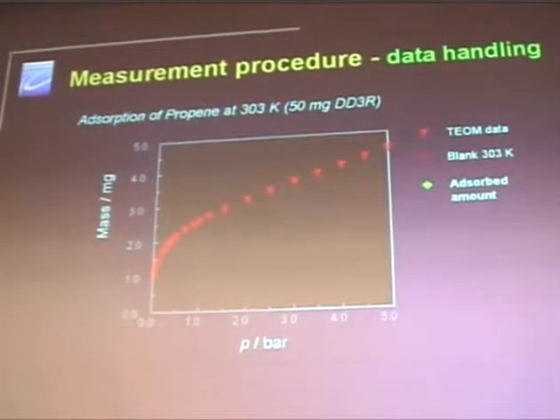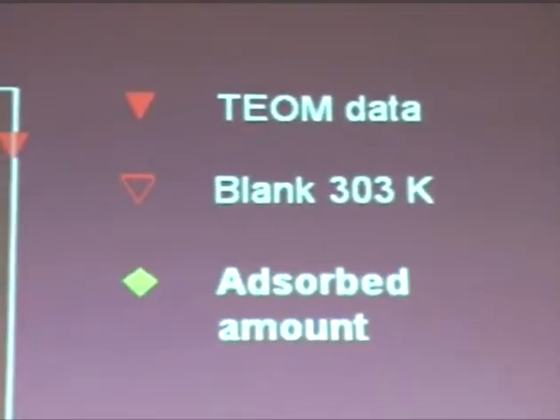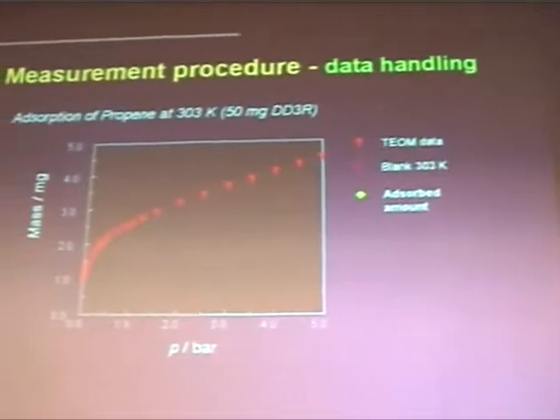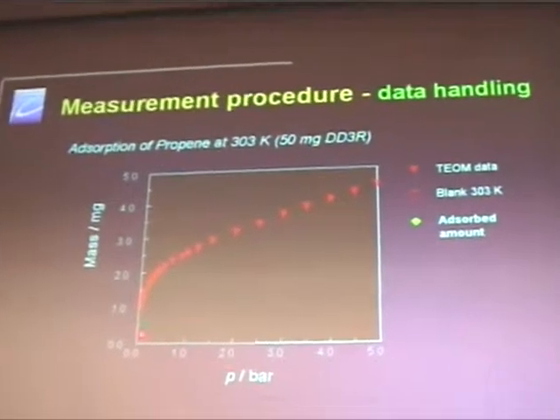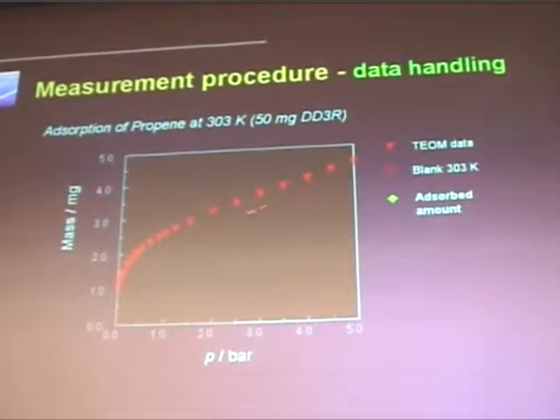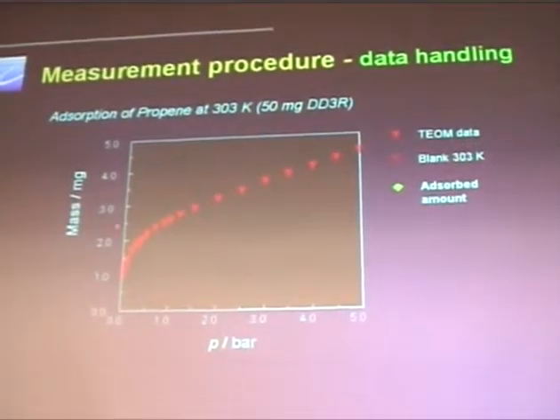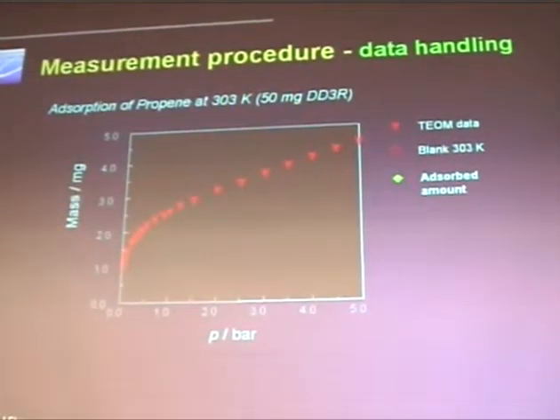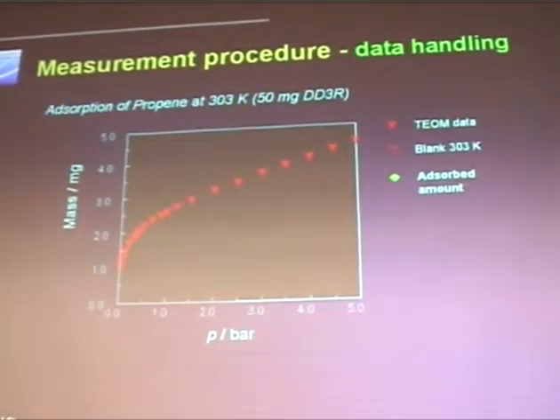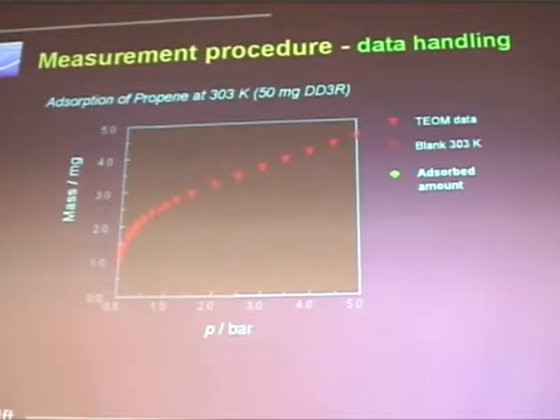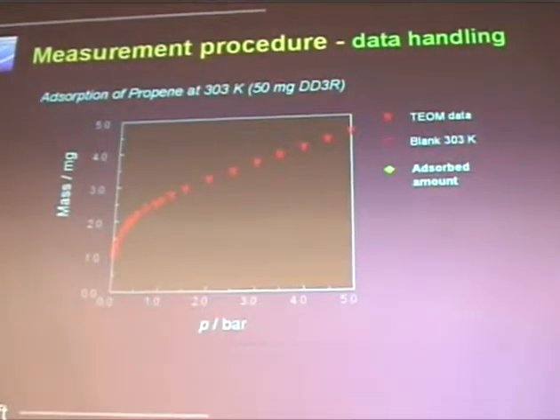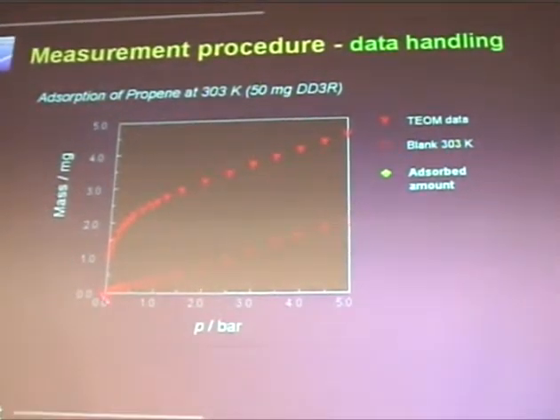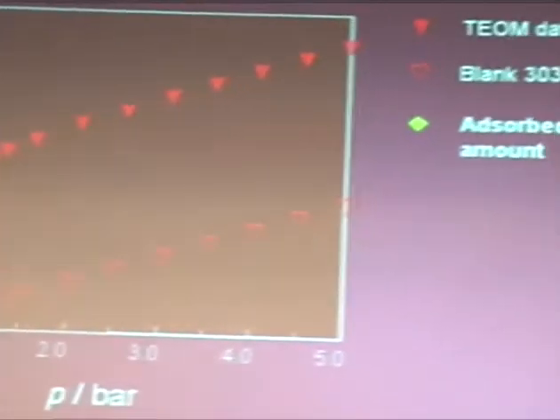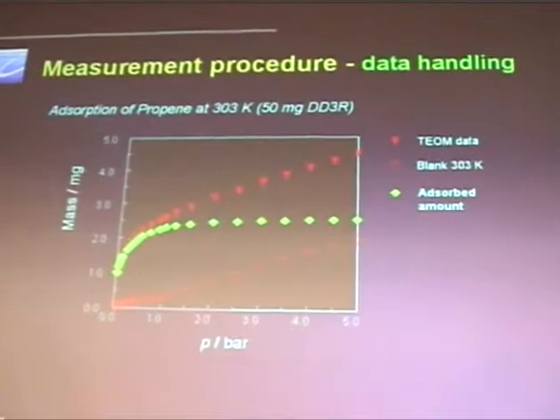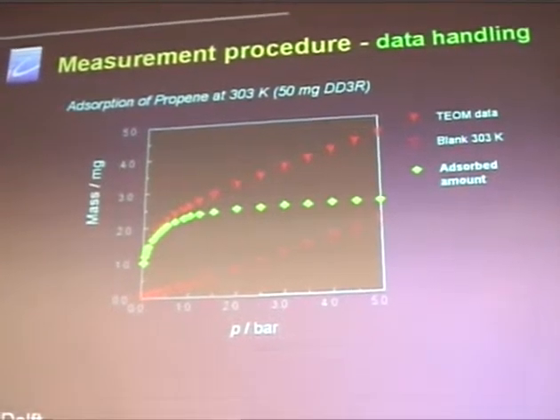Here is an example of propene adsorption in a certain zeolite. You see that when you increase pressure, these are the data you find on the equilibrium conditions. These are TEOM data. When you do a blank, meaning a sample that's, let's say, non-porous, with nothing adsorbed, you also find something, and you find that with the pressure the background also increases. So you have to correct it. When you correct it, you will have a very nice answer that you really can trust.